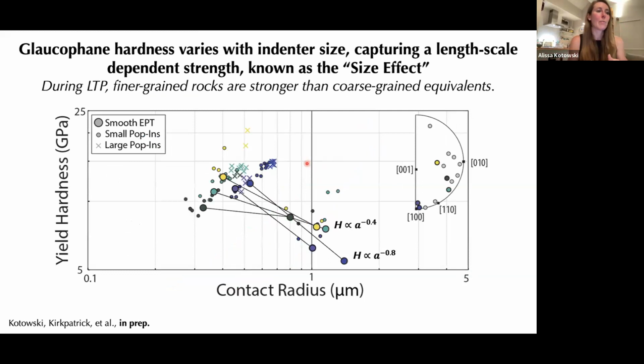By indenting the same grains of spherical tips with different radii, we can also demonstrate that glaucophane hardness is not only a function of grain orientation, which we expected based on its anisotropy, but also length scale of deformation. So for smaller contact radii or smaller indenter tips, the true yield hardness is higher than that for larger contact radii or indenter tip sizes.